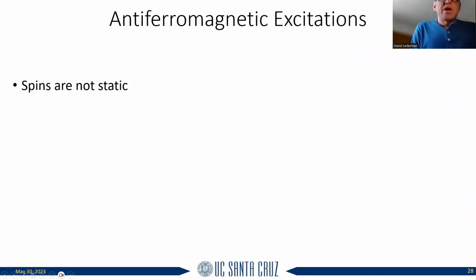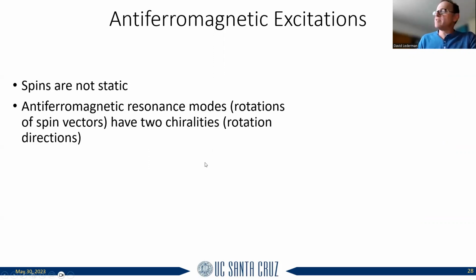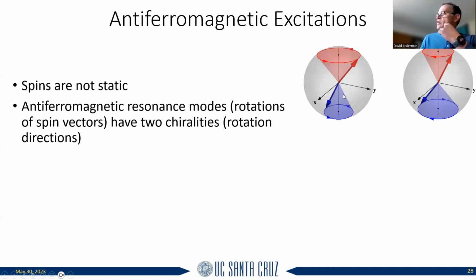Okay, so let's talk about these antiferromagnetic excitations, which we want to use to transmit information with. Spins are not static usually. In fact, in an antiferromagnet, you usually have some resonance modes. And what happens is, even in zero applied external field, you have modes where you can get precession about an axis, and this is due to the internal fields, and especially the anisotropy and the exchange field.